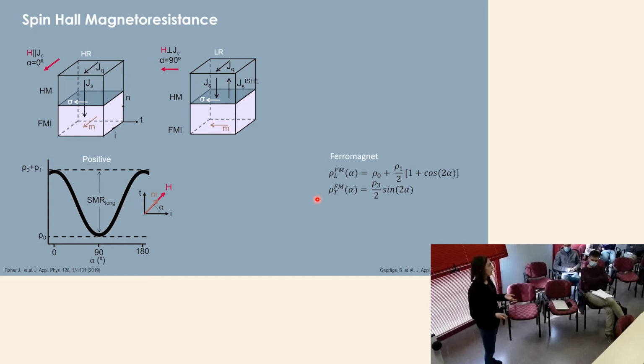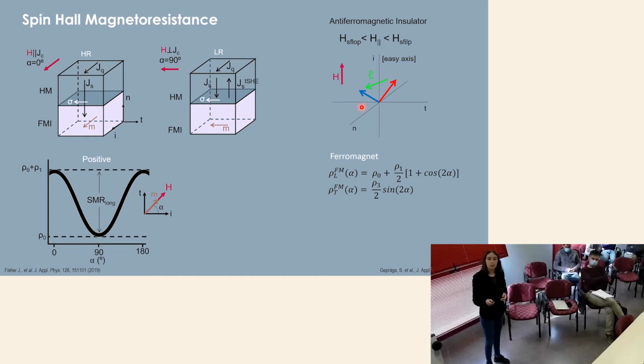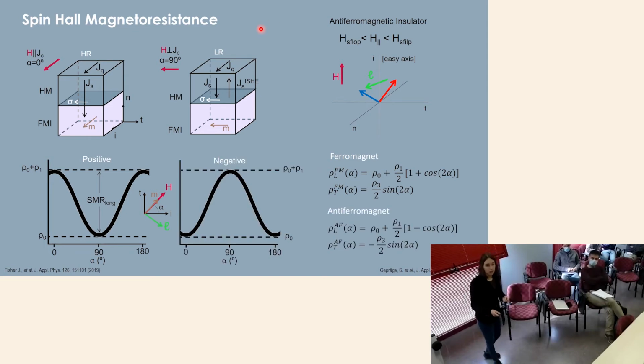Now, if this magnetic layer is not a ferromagnet, but an antiferromagnet, something slightly different happens. So here, if we apply a field which is large enough to have a spin flop transition in the material, we will have that the Néel vector is always pointing perpendicular to the applied magnetic field. So the result is an SMR which looks the opposite of the ferromagnetic one. So it has a negative sign in front of it. And conventionally, this is called negative SMR and has been seen in different antiferromagnets like iron oxide or nickel oxide.